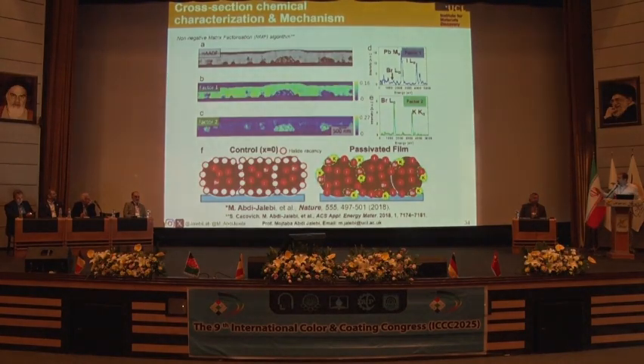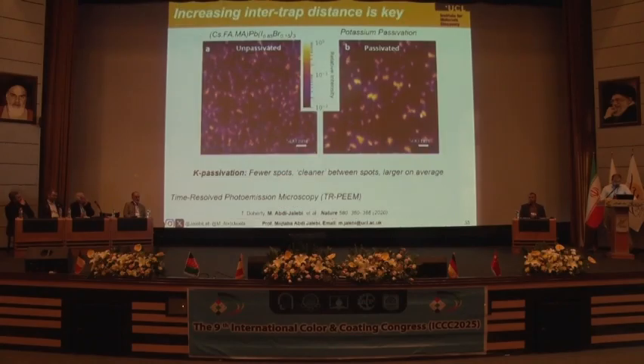And this is just to prove what I've just said. This is experimental proof for our mechanism. This is a high-resolution TEM of the cross-sectional solar cell, and you can look at the grain structure cross-sectionally. Here we can deconvolute the phases. One major phase we found, in particular at the interface, is potassium bromide, which is our passivating phase at the interface. So this is a proof for our mechanism.